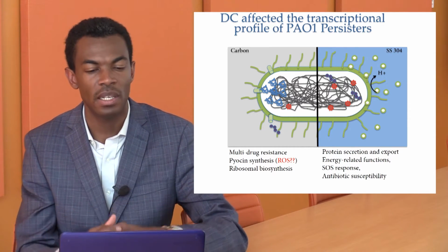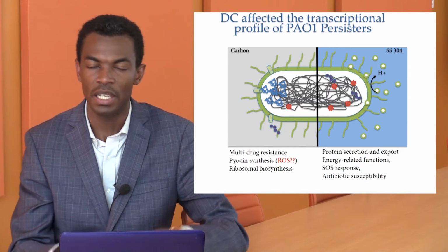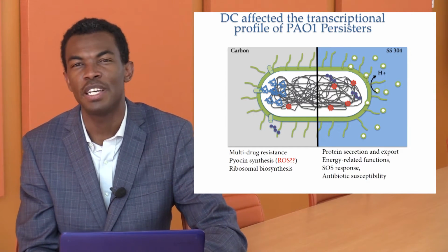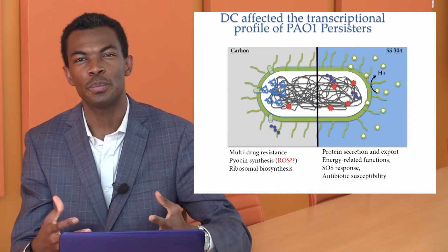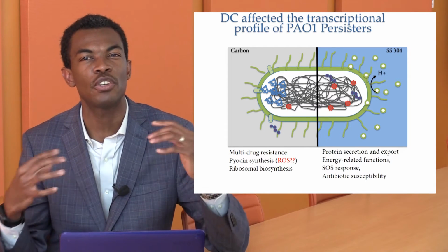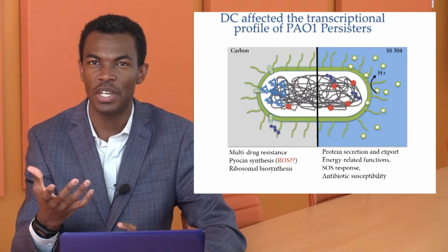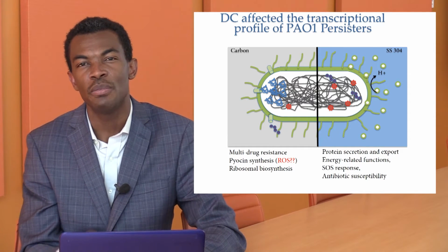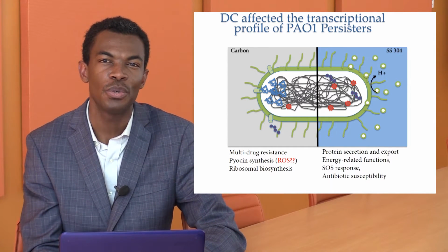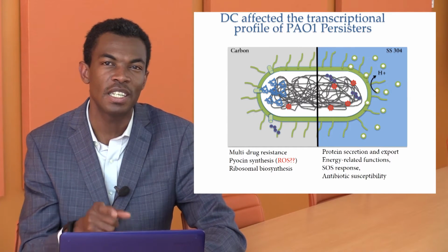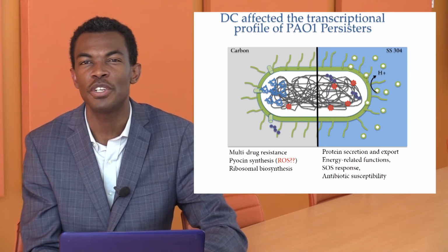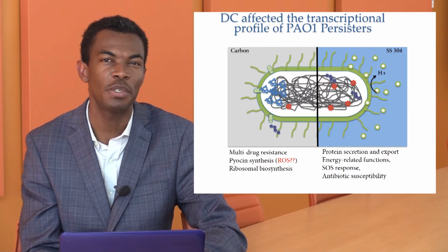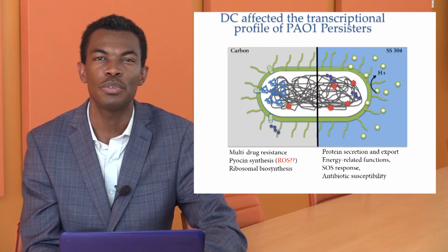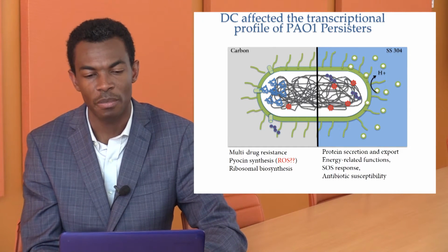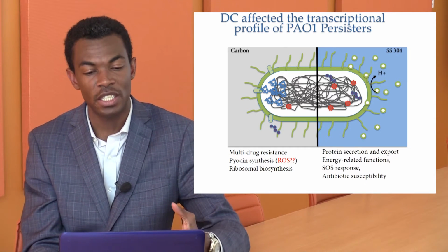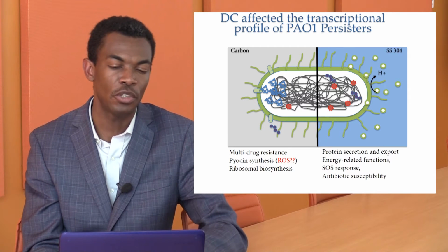Inside the cells, they accumulate the reactive oxygen species, which engenders what we call the SOS response, when the cell is trying to respond or get some relief because of the accumulation of some very toxic elements such as the reactive oxygen species. And finally, the cells treated with stainless steel electrode were very susceptible to antibiotics, and that's what the genetics shows. And this goes along with our previous finding that when DC treatment is performed with stainless steel electrode and antibiotic is supplemented to the treatment, we got a synergistic killing of the bacterial cells. So this is how we use genetics to confirm our vision and to better our understanding.